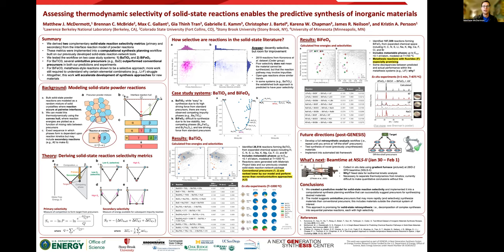We begin with a discussion of what these selectivity metrics say about existing reactions in the solid-state synthesis literature. We find that many reactions do score highly, but for certain target systems like barium titanate, the conventional precursors — barium carbonate and titanium dioxide — actually rank quite low.